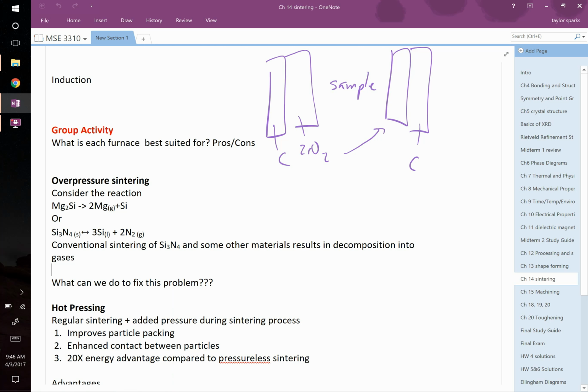By the way, silicon nitride actually does decompose pretty readily, right? At high temperatures, it will decompose this way, and at lower temperatures, it's susceptible to interacting with water and air. If you take silicon nitride and put it in a little Tupperware with air, even in Utah where we're very dry, there's a little bit of moisture in the air. It reacts with it and forms ammonia. So when you open it, you'll smell ammonia, and you're actually decomposing your silicon nitride over time.